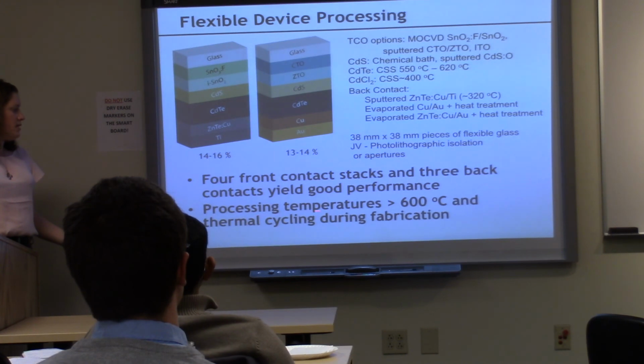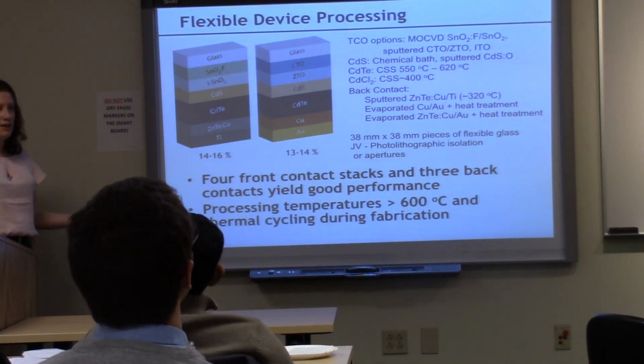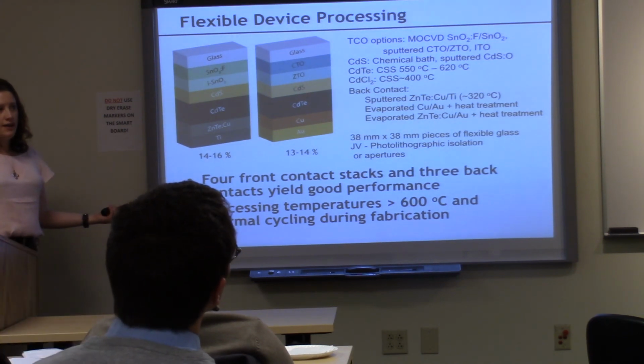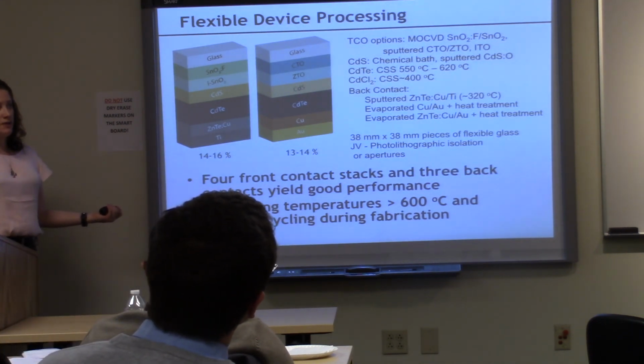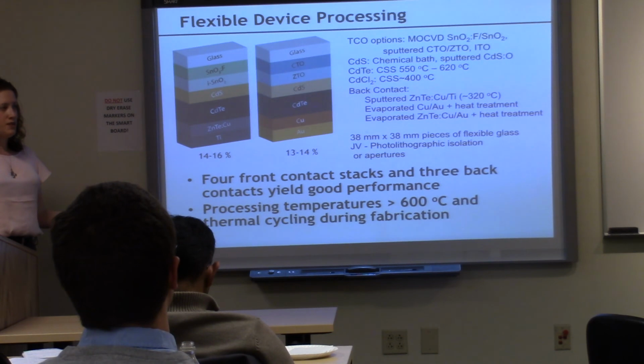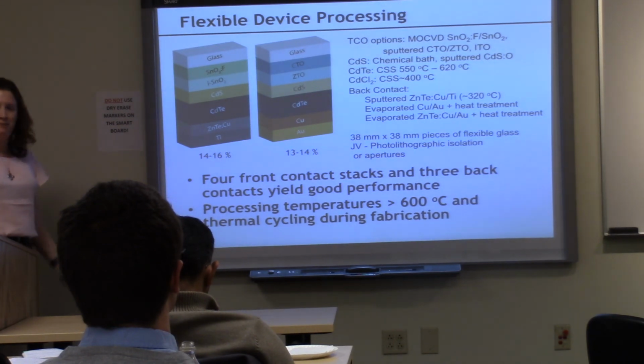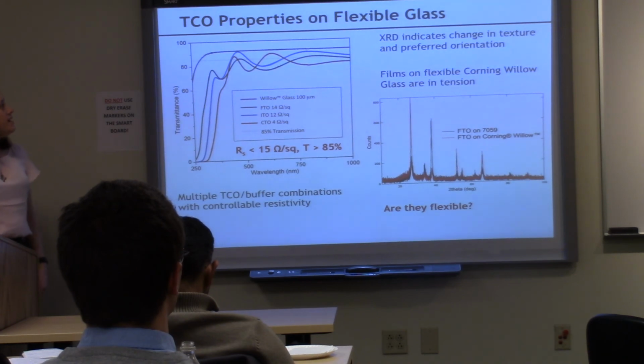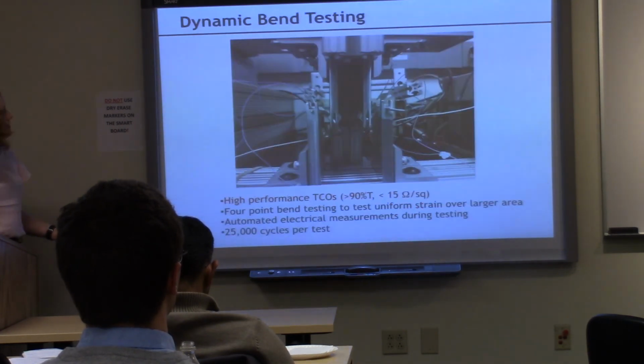And this was a slide I made a while ago when everybody said this glass would break. If you cycled it like this, you can't handle it. We've made hundreds of devices. You can break them if you put a probe on them too hard, or if you do something really dumb. We joke that the higher your rank in our organization, the faster you will break a piece of glass. So an associate lab director will break it in under 30 seconds. We haven't given it to a director yet. That'll probably be spontaneous.